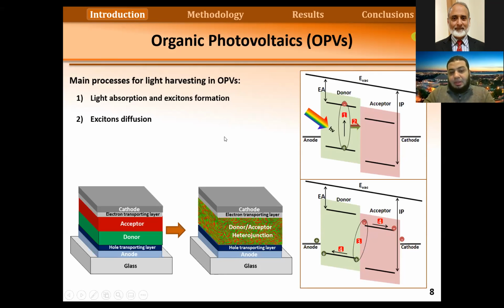So the main thing that happens is we have light absorption, and then the excitons, after forming, have to diffuse to the interface, and then they dissociate at the interface, and after dissociation, they have to move to the electrodes. Also, organic semiconductors have another limitation, which is the diffusion length. The charges can't move a large distance before they recombine. So the excitons might recombine very early. So if we use a bilayer, like a donor and acceptor on top of each other, we will not be able to have efficient solar cells, because we also have a low interfacial area.